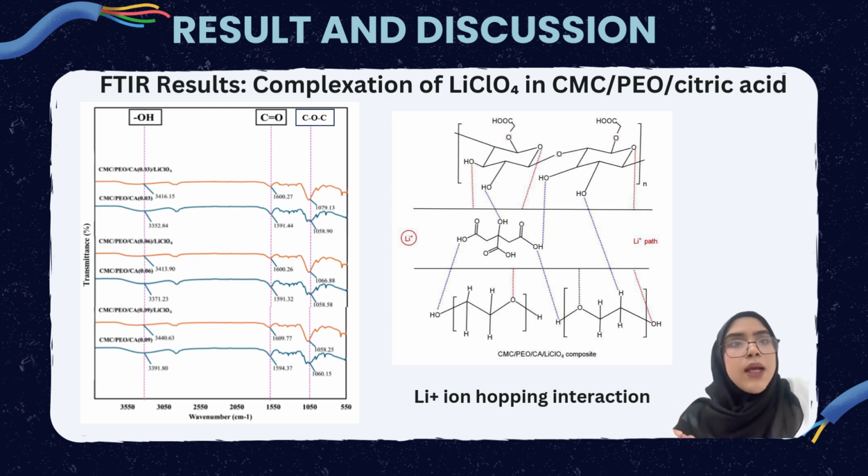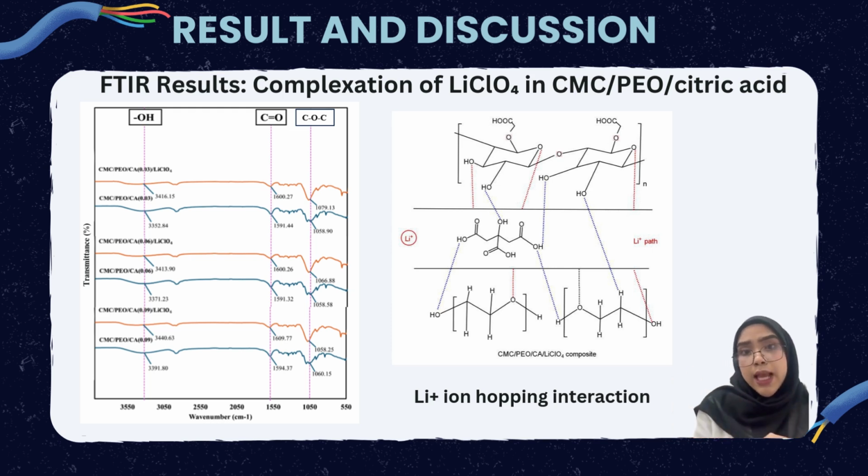In COO, the effect of Li+ ion bonding with carboxyl oxygen increases the bond stiffness while lowering the COO electron density. But at COC, there is no significant shift because of the lower affinity of lithium for it than for the hydroxyl and carbonyl groups.